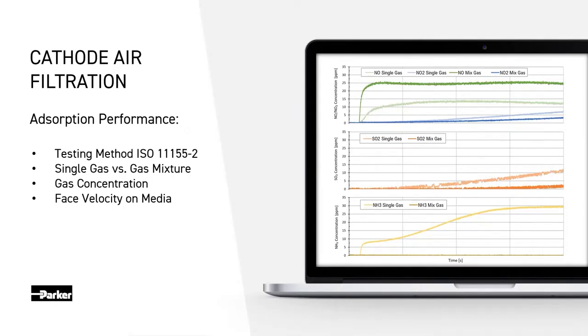For example, as mentioned, this ISO test is conducted on single gases. However, in the environmental air, there is always a mixture of gases. We have conducted several tests to compare the performance of single gas and gas mixtures, and this has a major impact on the performance of the filter. Similarly, the gas concentration will have an impact. The higher the concentration, the lower the efficiency of the filter. The ISO standard has a high concentration to make sure that the test can be finalized in a certain period of time. However, in real-life conditions, this concentration is significantly lower, and this will also have a major impact on the filter. The third point would be the face velocity on the media, basically how much of the air flows through a certain amount of area of a filter. This is critical because this needs to be tweaked correctly to make sure that you have the optimal gas performance and the optimal size of such a filter.